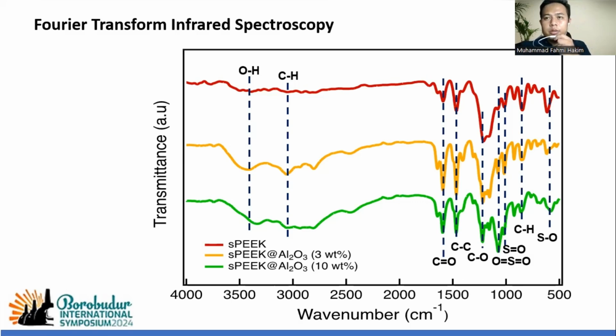The addition of aluminum oxide caused the peak wave number to reach 1217.03 per centimeter. Both SEM and FTIR analysis revealed that aluminum oxide enters the membrane, with FTIR analysis demonstrating the water and methanol absorption ability of the membrane regarding water uptake, proton conductivity, and methanol permeability.